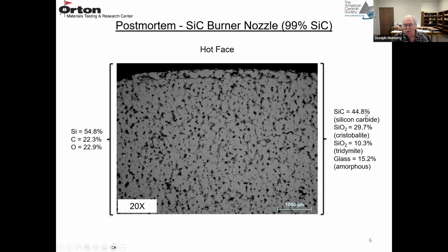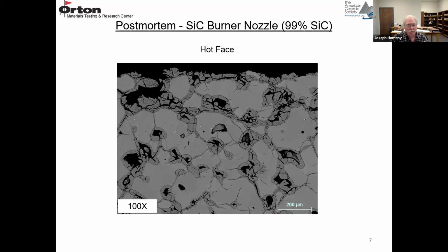So about 55% of the silicon carbide has disappeared. It's in the form of cristobalite, about 30%, tridymite, about 10%. We talked about these two high temperature forms of silica. And then there's a silica glass also about 15% is amorphous. So the silicon carbide has been oxidized to these two forms of silica plus an amorphous silica glass.